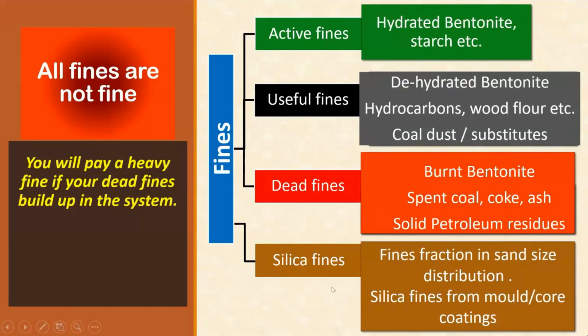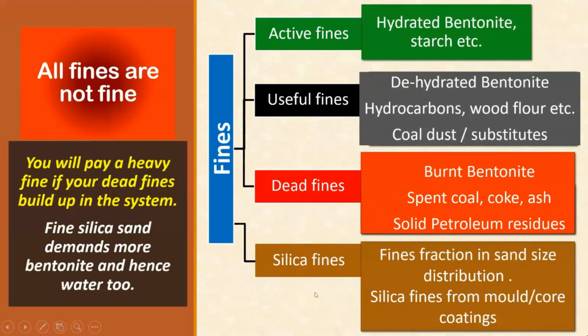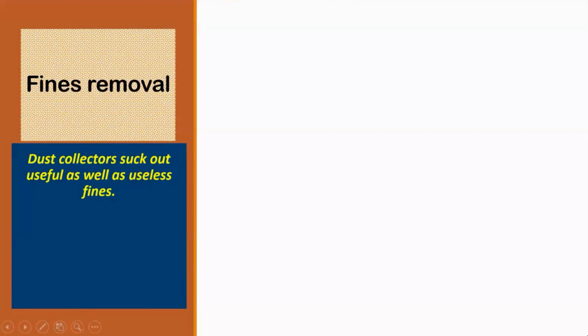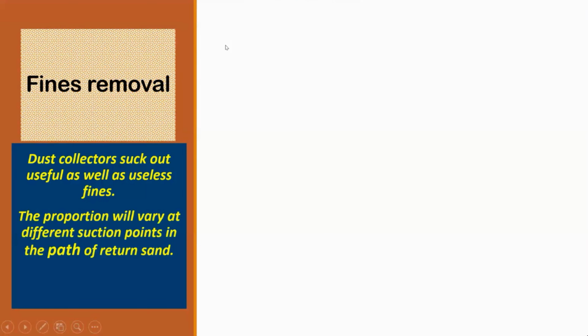Now this silica fine dust is also having a lot of surface area, and then it demands bentonite, and that bentonite demands water. So we have to control all these fines so that your excess moisture is taken care of. How do you remove the fines? Dust collectors suck out useful as well as useless fines. So the proportion will vary at different suction points in the path of the return sand. So that has to be done by careful analysis of the sucked out fines, how much of the fines are active, how much of the fines are inactive at various places. And accordingly, you adjust the suction system and then blend them if you require them.